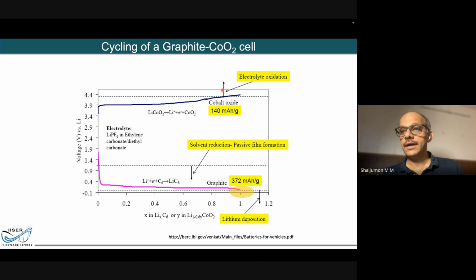Because I cannot go beyond this, because you're using a liquid electrolyte here. So if I go beyond this dashed mark here, the electrolyte will decompose. It oxidizes, and it releases some gases, right? And when it releases gases, then finally what will happen is it just gets blown up. And that's what you get to see here. You keep charging repeatedly overnight, you can see that the battery starts bulging, right? Because some gas evolution has happened, and that's why the battery gets bulged. And finally, it would blow away.